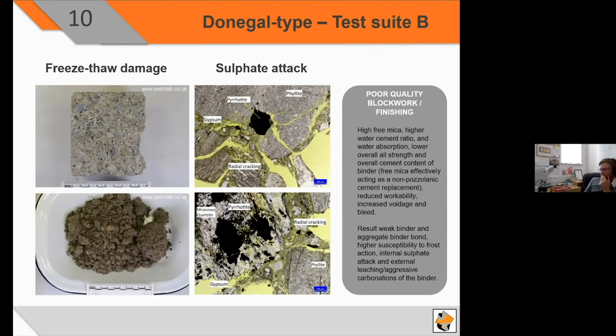Additionally, one of the things that is notable in both types is poor quality block work and finishing. Specifically within the Donegal type, quantities of free mica, high water cement ratios, and water absorption lead to an overall reduction in strength, with the cement content being diluted effectively by the free mica, acting as a non-pozzolanic cement replacement, reducing workability, increasing voidage and bleed, and reducing the effectiveness of the cement binder. The resulting weak binder and the aggregate bond make it highly susceptible to frost damage, internal sulfate attack, and aggressive leaching.